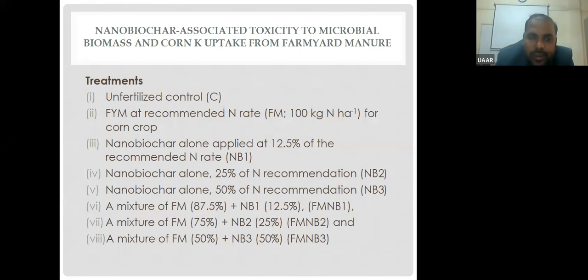Next is nano-biochar associated toxicity to microbial biomass, corn K uptake from farmyard manure. So there is actually a treatment on unfertilized control. Then we applied farmyard manure at recommended N rate, which is 100 kilogram nitrogen per hectare for corn crop. Then it's nano-biochar alone at 12.5% of the recommended dose. Then is 25%, then is 50%, and then a mixture of farmyard manure replaced with nano-biochar: 87.5% farmyard manure and 12.5% nano-biochar, and 75% farmyard manure, 25% nano-biochar, and 50% farmyard manure, 50% nano-biochar.